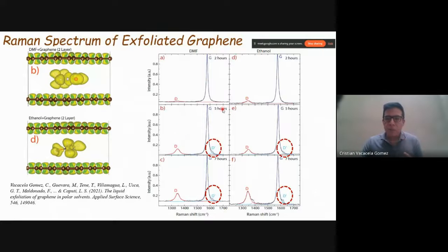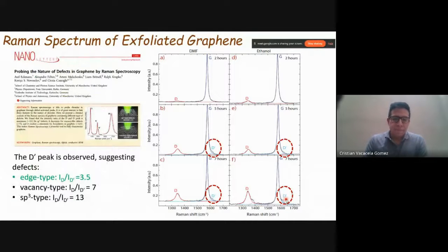But the important thing here is that after 5 hours of sonication, another peak appears. That is the D prime peak, for example here, here, here, and here. This is an extra peak, and it is also an indicator of defects induced in our exfoliation process to prepare graphene dispersions. So the D and D prime peaks are connected with the defects in our graphene samples. But what type of defects? If you remember, we talked about basal defects, in-plane defects, and vacancy defects. But this work gives light on how we can identify or interpret the defects induced after your exfoliation process.